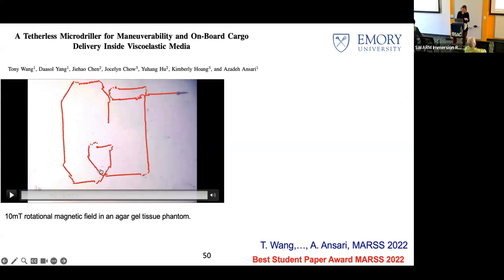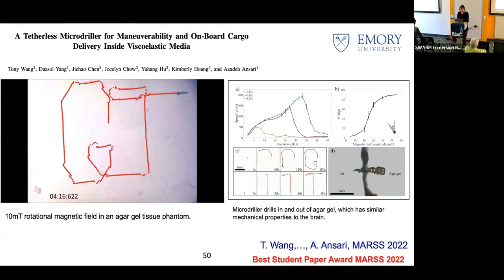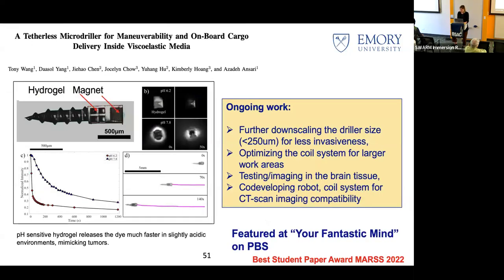You can still see that there's a lot more closed loop control that needs to be done for more precise manipulation, but this was still pretty cool in the sense that you can go from air into the gel, and that the speed is controllable with frequency. Again, all of these give you a lot of control if you want to do swarms or individually address these robots. And then what we did next is that we added a hydrogel that can have drug in it.